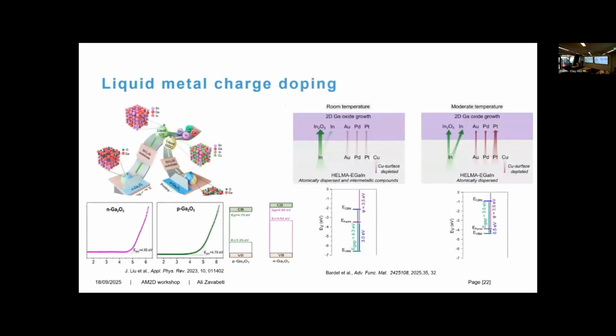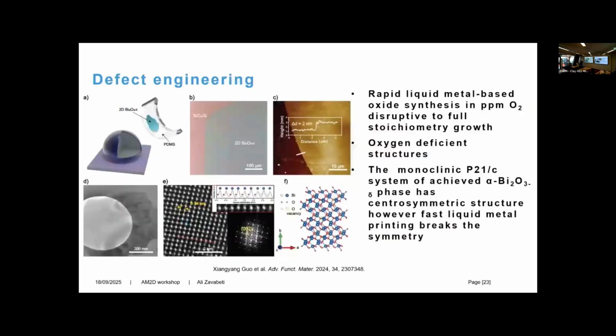Another opportunity is the doping. We can change the doping of these layers. We've shown that if we add certain elements, there is a competition for them to come to the surface and appear in the oxide. For instance, for gallium, we can print n-type gallium oxide, and then by adding some elements, we can make a p-type gallium oxide, which is again great. So, for defect engineering,